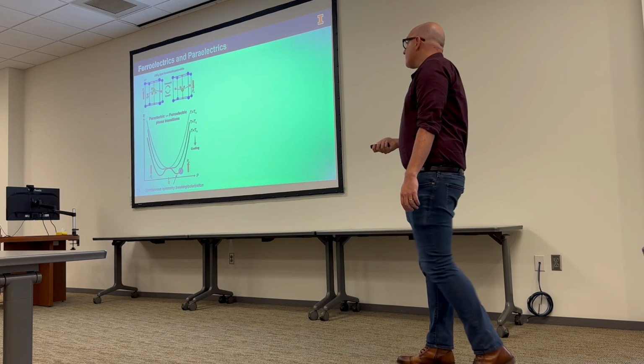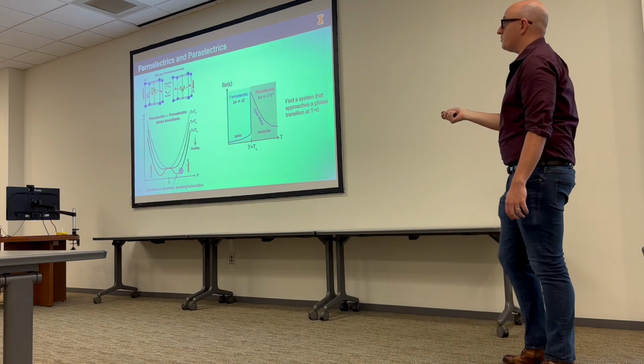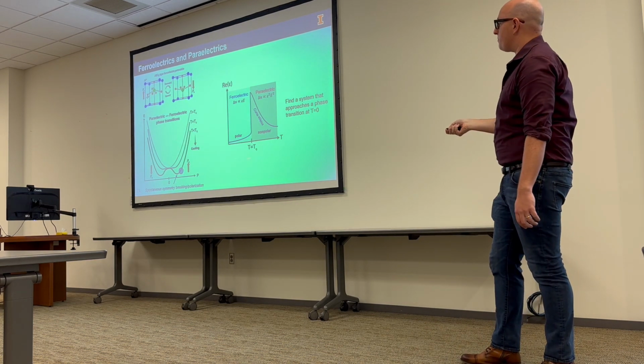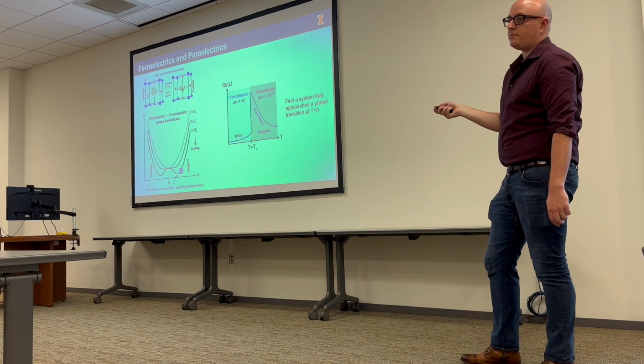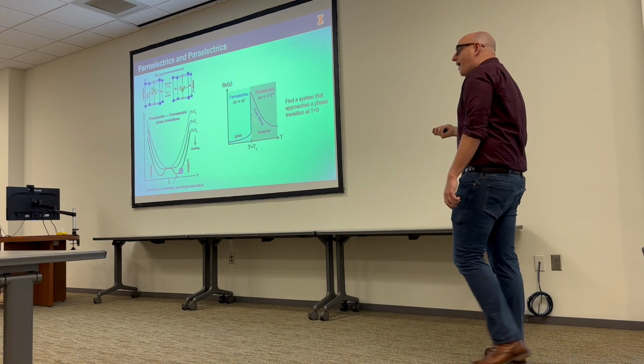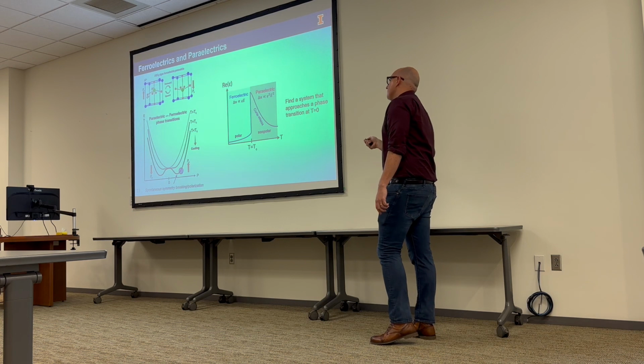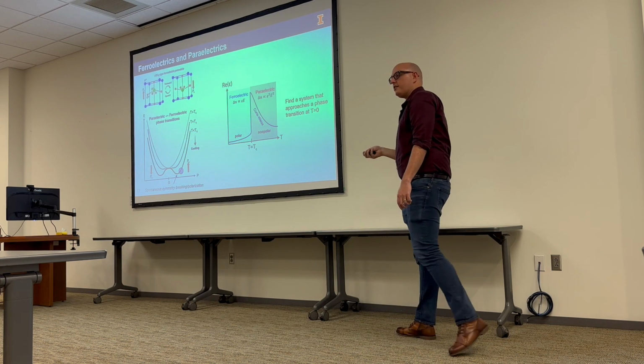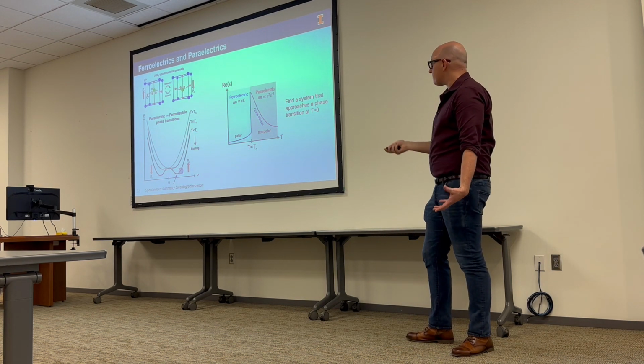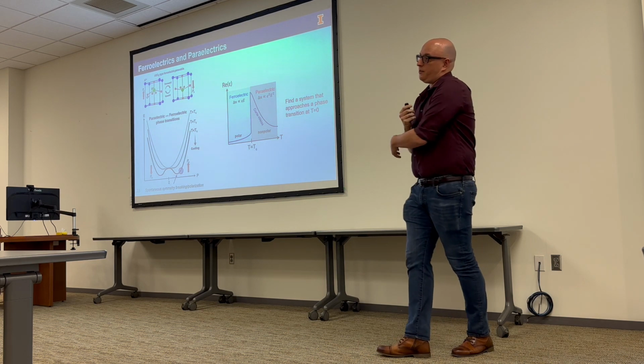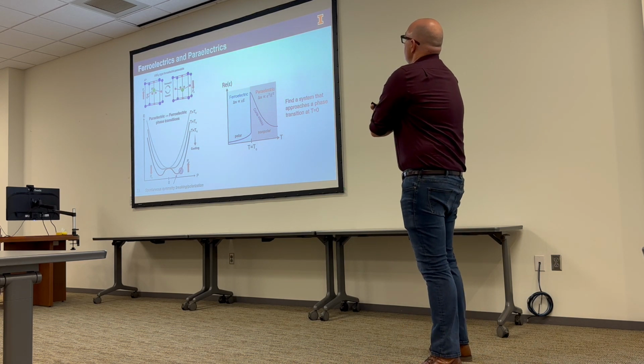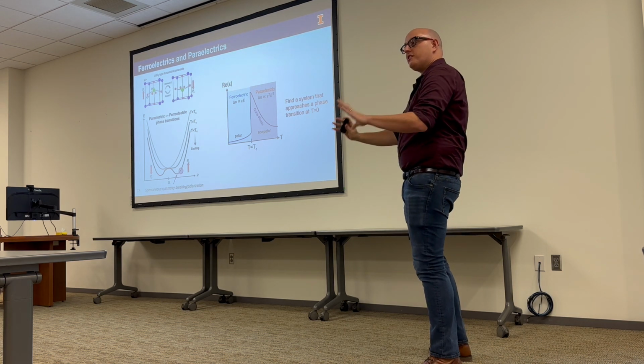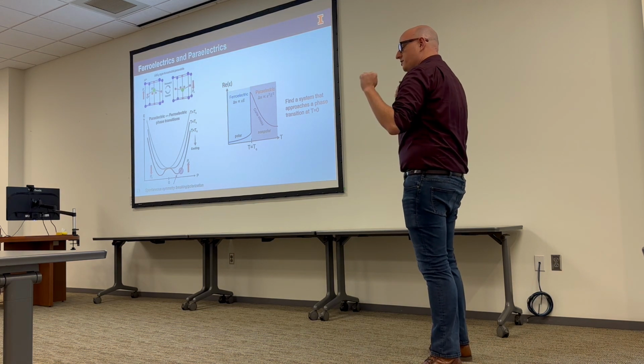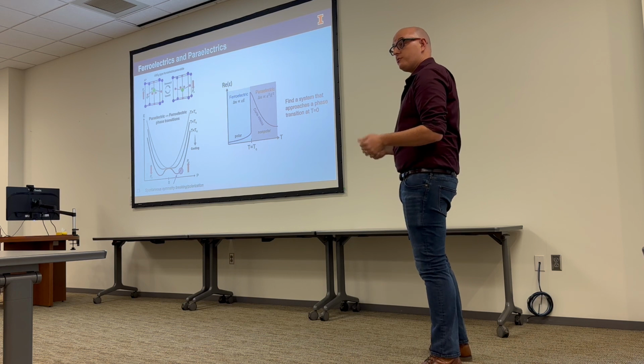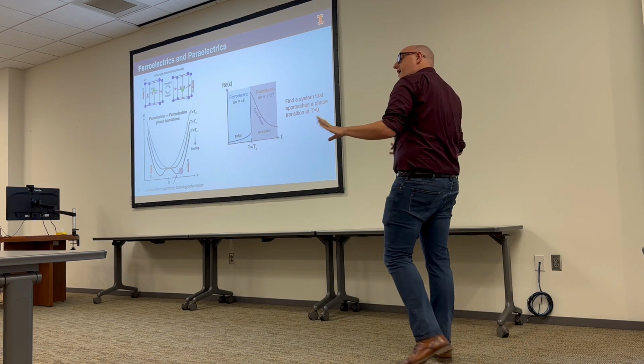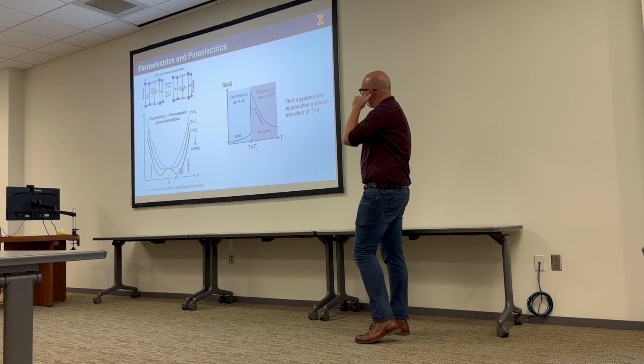What that means in practice is that the dielectric constant, or the epsilon of materials, blows up as I approach TC. And so if I want to engineer a high dielectric constant, I want to find a system that approaches a phase transition. And in this case, I want that to be near zero temperature for quantum physics. And so I want T to be close to zero. So we've understood the physics that's guided us to this fundamental thing, which is we just want to find low temperature phase change materials. Once we can do that, we can do awesome nonlinear optics at low temperature.